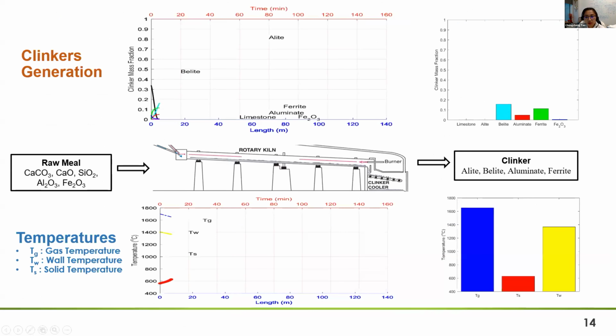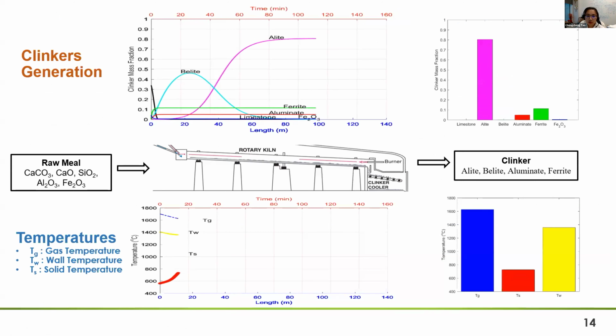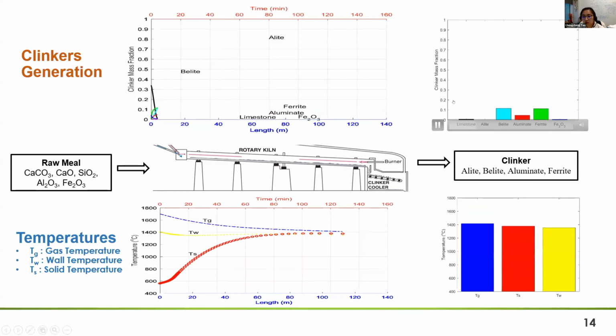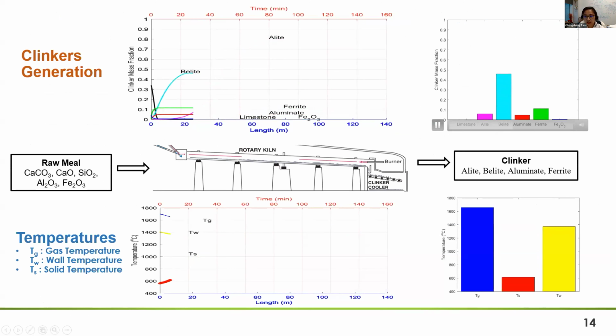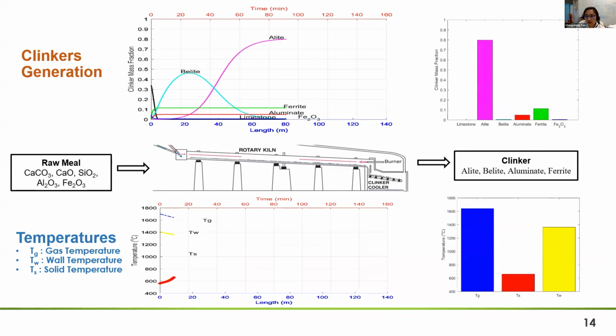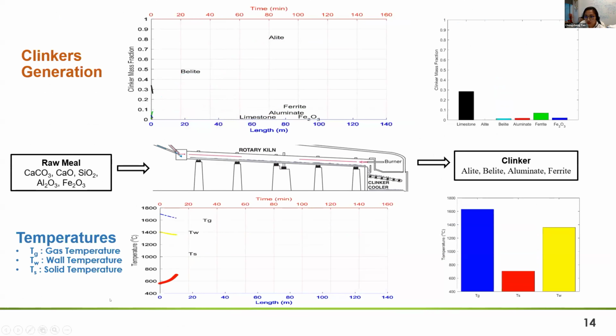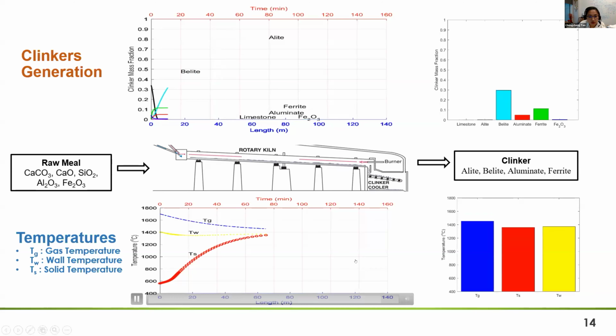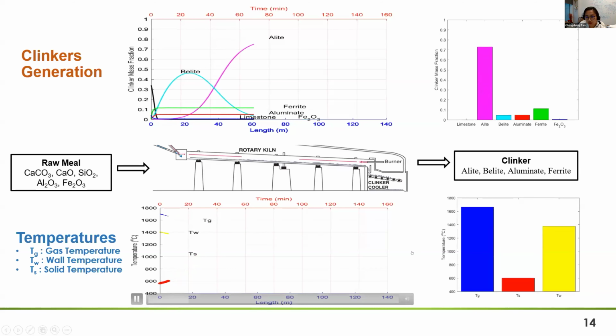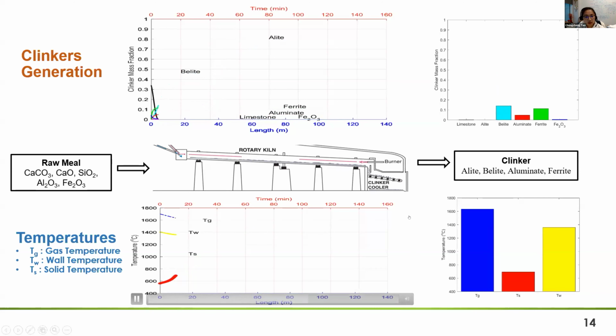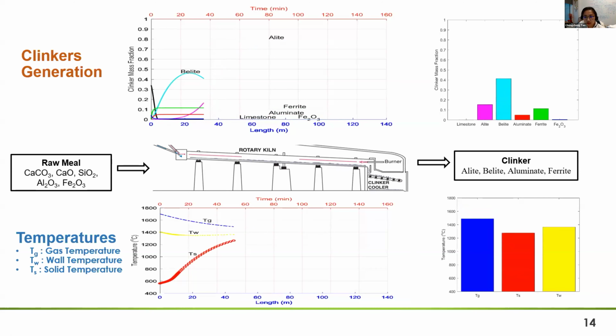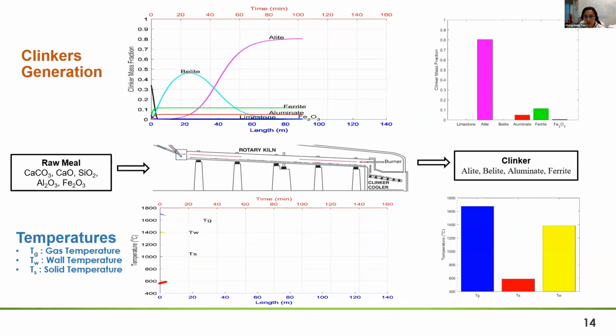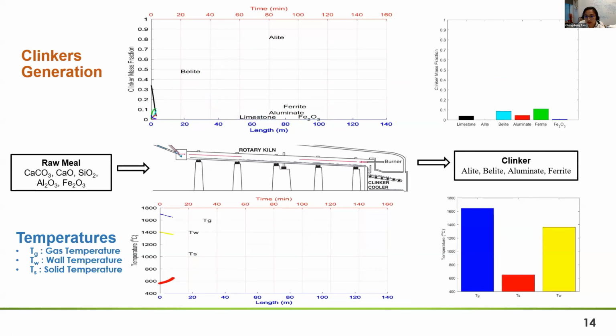So here is a demonstration of the virtual cement plant simulation result. The top 2 animations, the top 2 figures, show how the mass fraction of the cement clinkers is generated inside the kiln. And the bottom 2 figures show how the temperature profiles for gas, for the kiln wall, and for the cement solid change inside the kiln. We could see that the 3 temperatures become uniform after the heat transfer process finishes.